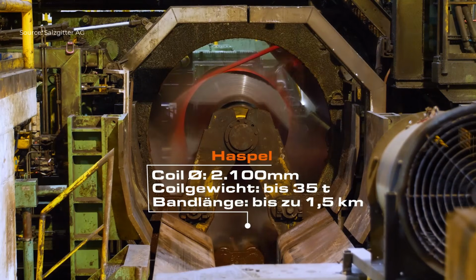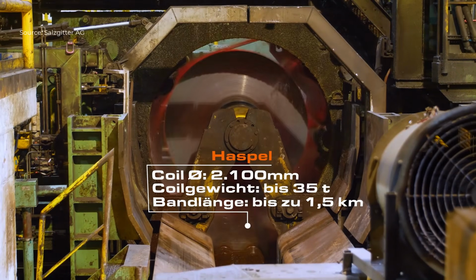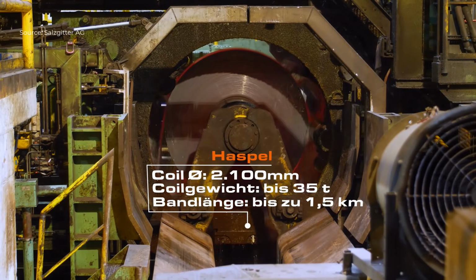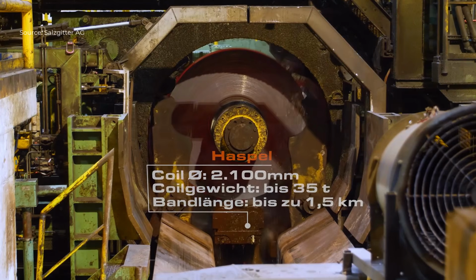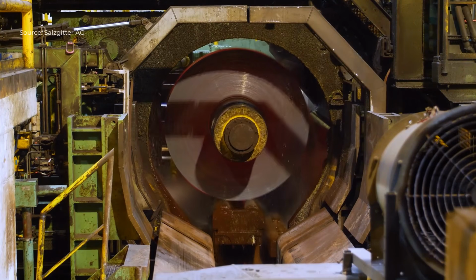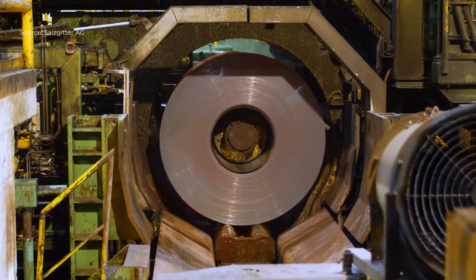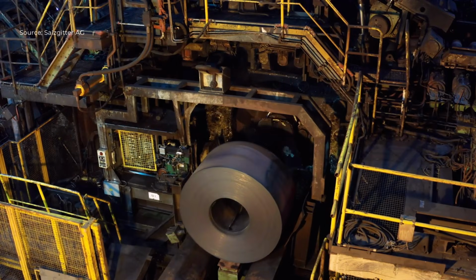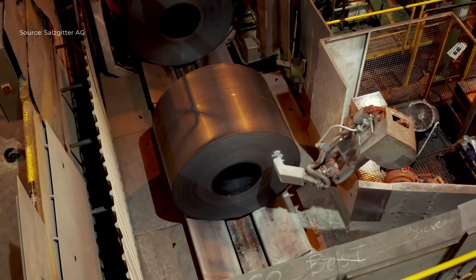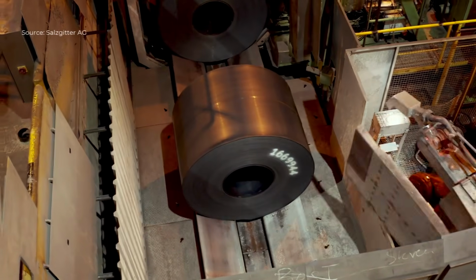Finally, the cooled strip is wound on a coiler, haspel. The finished coil can reach a diameter of 2,100 millimeters, a weight of up to 35 tons, and an impressive strip length of up to 1.5 kilometers, completing the transformation from a single steel slab into a continuous steel coil.